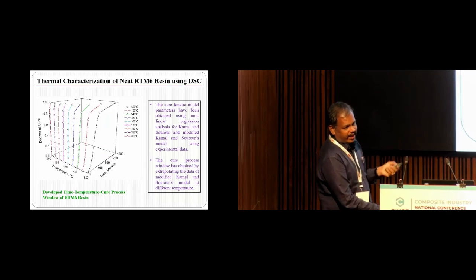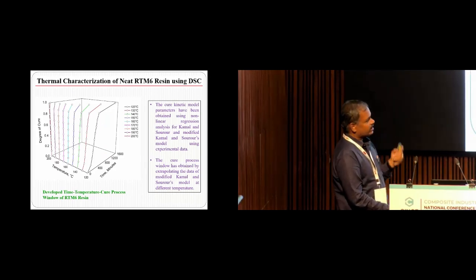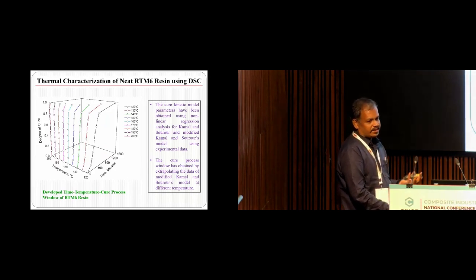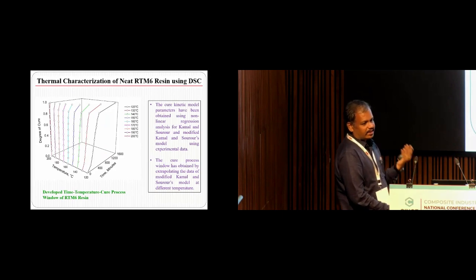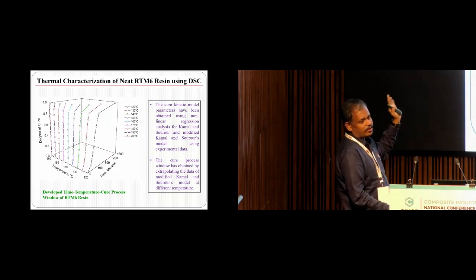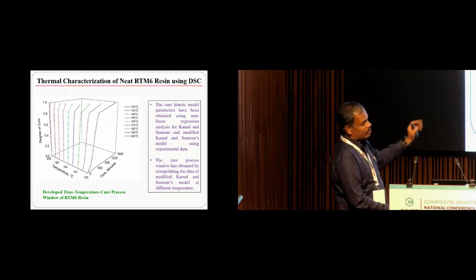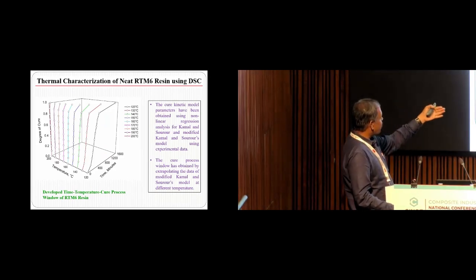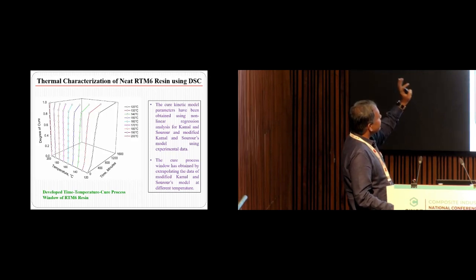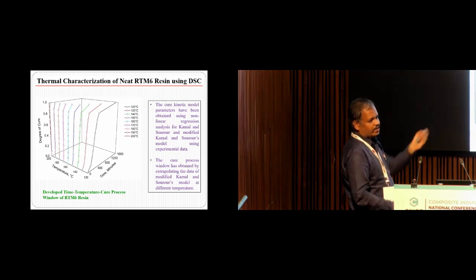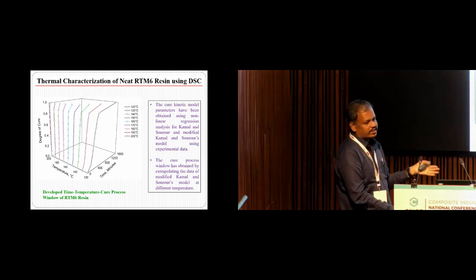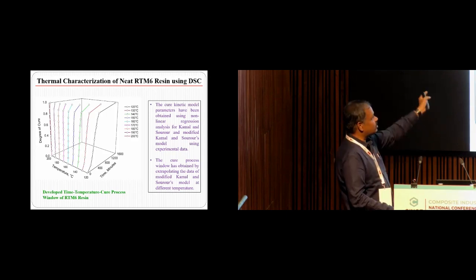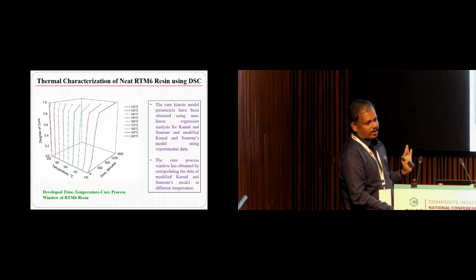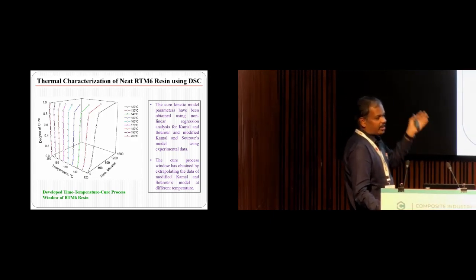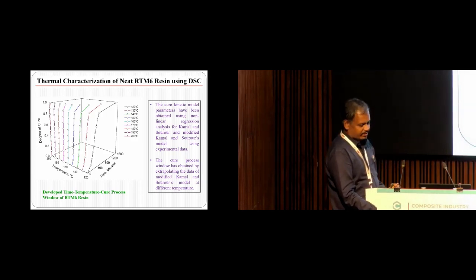So with the kinetic parameters k as a function of temperature, I can extrapolate. What are the kinetic parameters? In the Arrhenius equation, they are the frequency factor and the activation energy. Using those two factors, I can extrapolate, and I have defined the complete cure process window for the RTM6 resin. You can see it is defined from 120 degrees centigrade to 200 degrees centigrade, with times of a few hours. If I choose my cure cycle as 140 degrees centigrade for 3 hours, then without performing the experiment, I can extrapolate from this data and tell the degree of cure. So with only 4 different data sets, I can explore the complete kinetics of RTM6 resin.